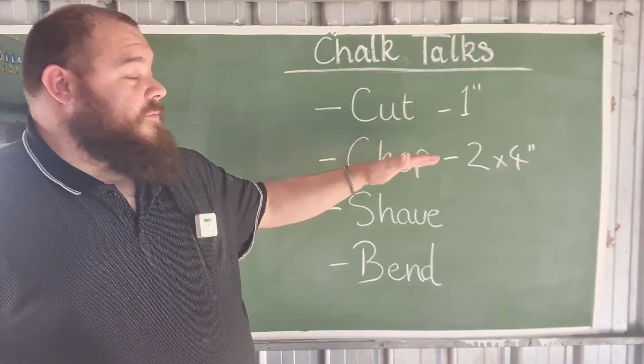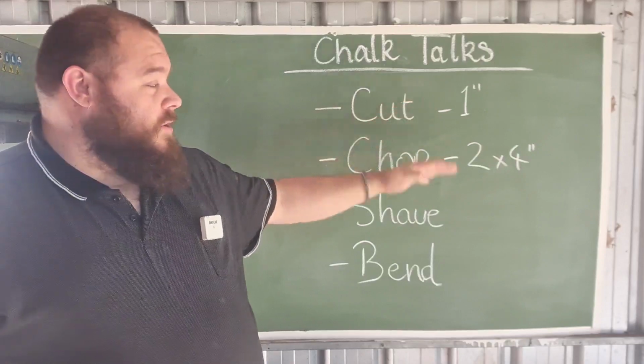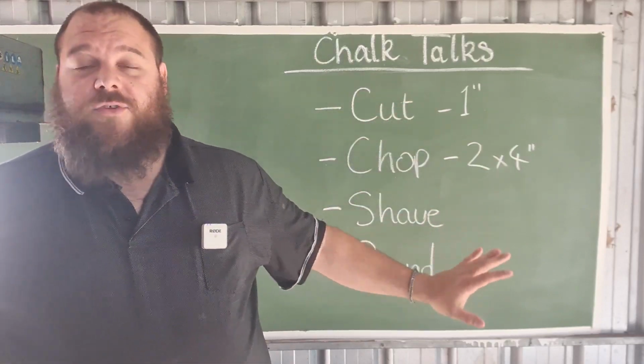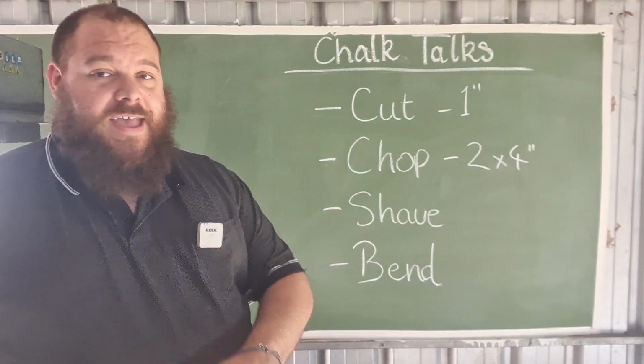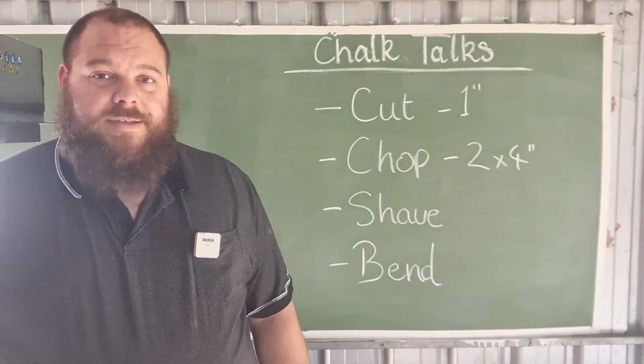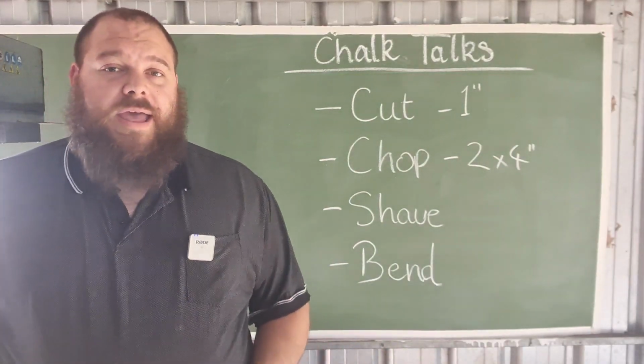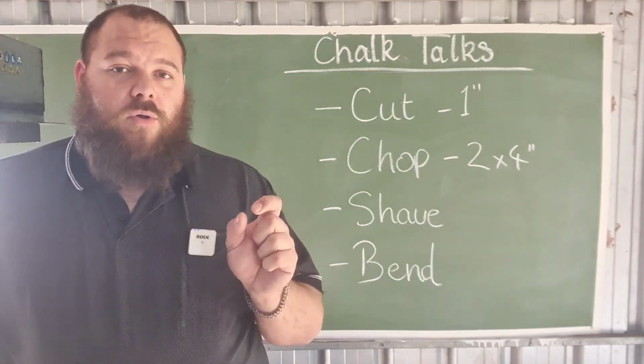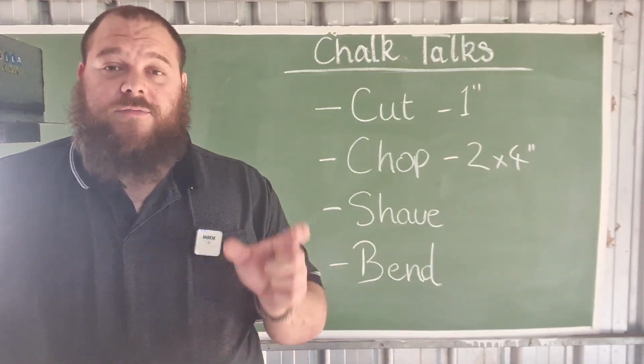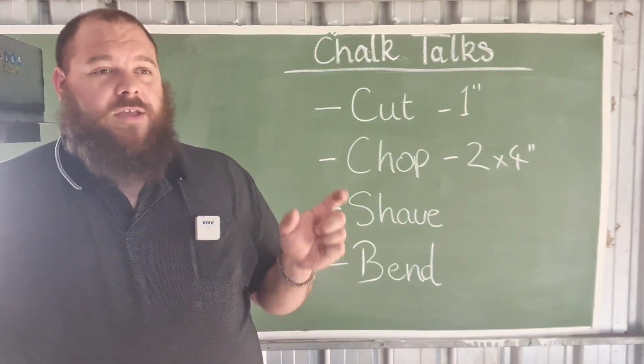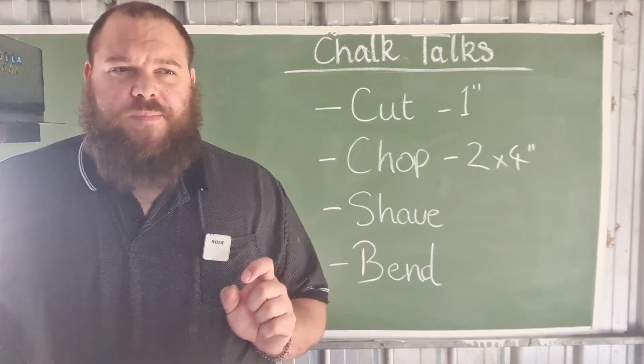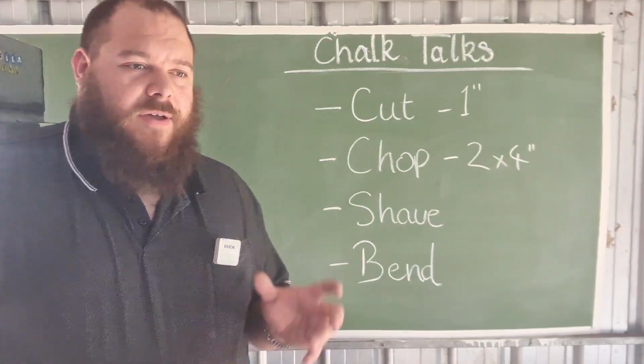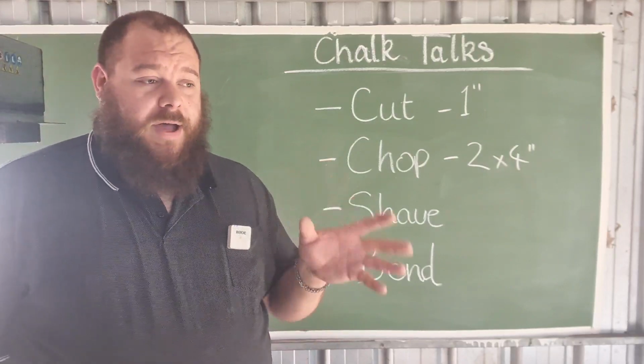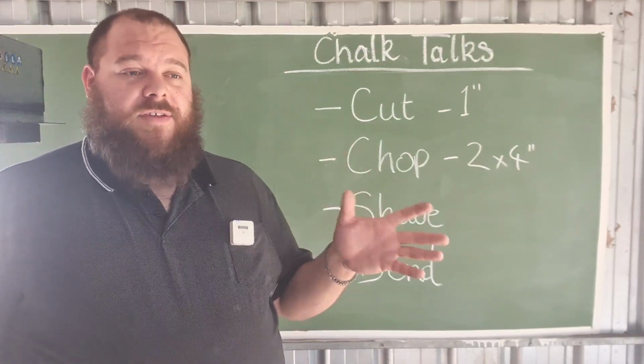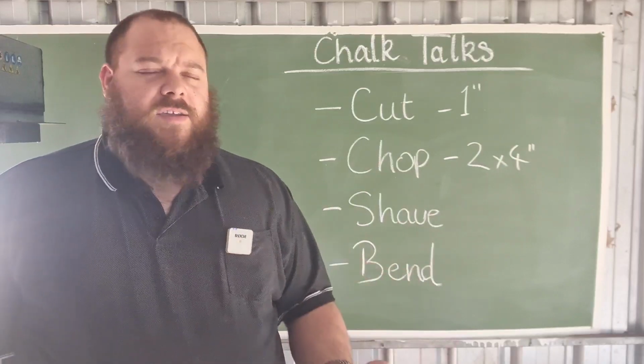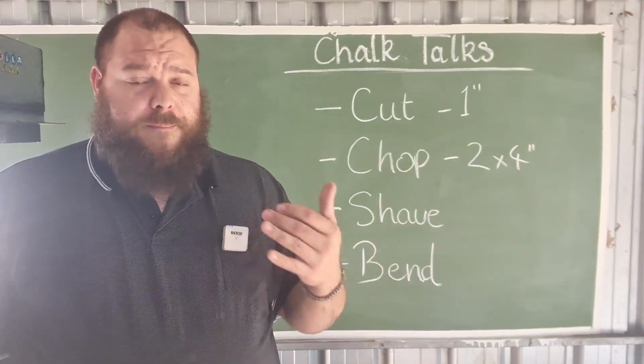So, chop the 2x4 twice. After you've cut the 1-inch hanging manila rope, you shave your arm hair, and it does shave. You have passed all of those processes. You get to the scary bit, which is the bend. Now, in the bend, you are allowed to have a crack no more than 1/3 of the width of the blade. So if your maximum width is 2 inches, then your maximum crack depth, I believe, is 0.66 of an inch, if I'm remembering correct. But that being said, if it does crack that much, there may be some annotations by the mastersmith on something like that, but it is allowable.